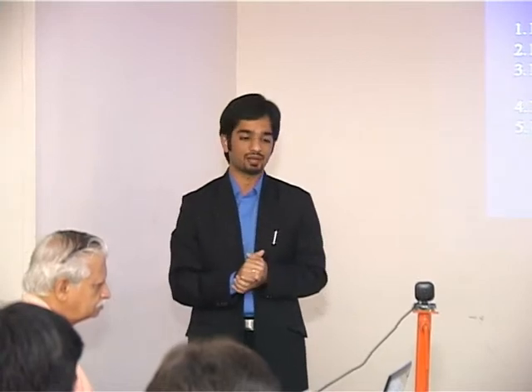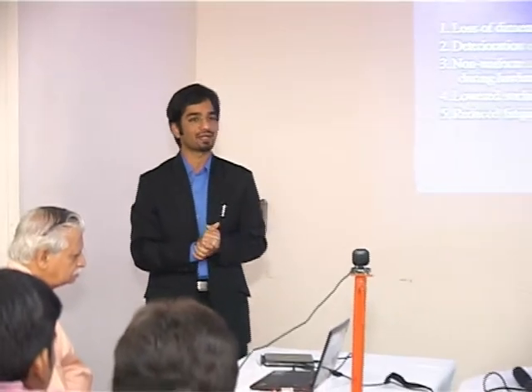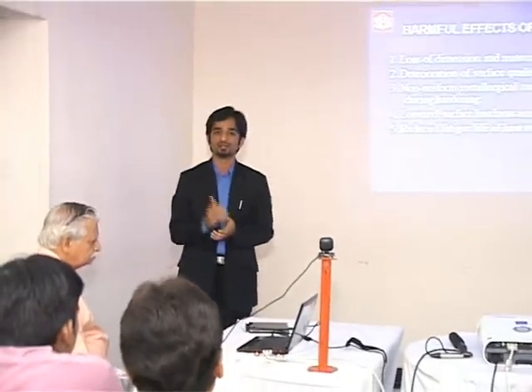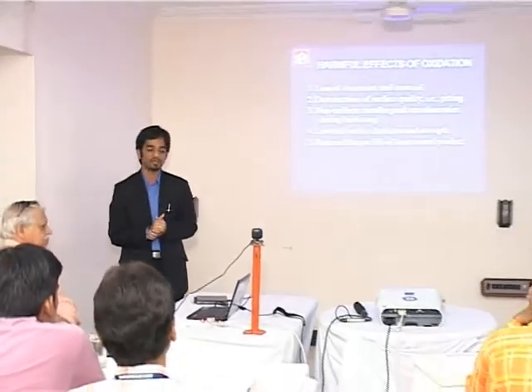Non-uniform metallurgical transformation during hardening, lowered surface hardness and strength, reduced fatigue life of the component. This is especially in the case of leaf springs, which are used in automobile suspensions, where if you need a certain number of cycles from a leaf spring, and we have decarburization or scaling introduced into that component, the cycle life is considerably reduced.